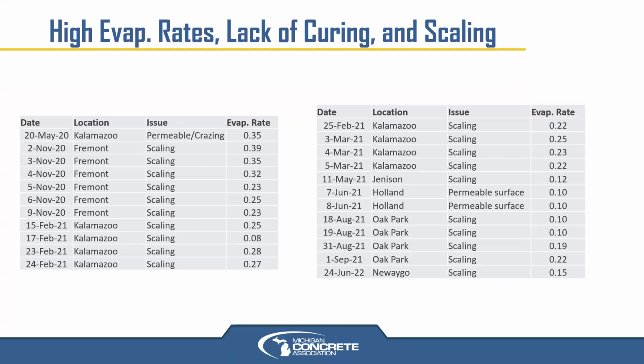And here's the data that show that, because these were high evaporation rate days, that caused issues. And primarily, in West and Southeast Michigan are the projects that I've looked at a few years ago. So I went back through my data and all the reports that I had produced for some of our members that asked for some of this assistance, and the pour dates listed, and we got weather station data and looked at evaporation rates. And yeah, most of the time when you have a surface issue, regardless of what's in the concrete, evaporation and lack of curing are the two things that go hand in hand.